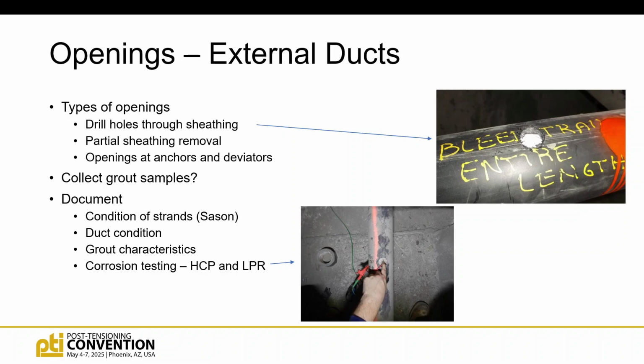So with the hole saws, because those are the easiest, you can see here on the left we've written down bleed trail entire length. So what that means is there's a small void that's on the top of that HDPE pipe, above the grout and below the entire interior diameter of the pipe. And generally they're small. They're 1/16, 1/8. They're not huge voids, but they're there.